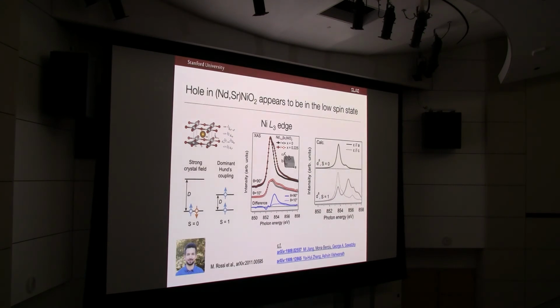Another important question is, what is the nature of holes in this compound when we substitute strontium? For example, in the 214 nickelates, it turns out to be in the high spin state. A number of people, here are some early ones, worried about whether or not you're close to this high spin and low spin transition. For those of you not familiar with the details, the idea is very simple: we start out with these d9 electrons.